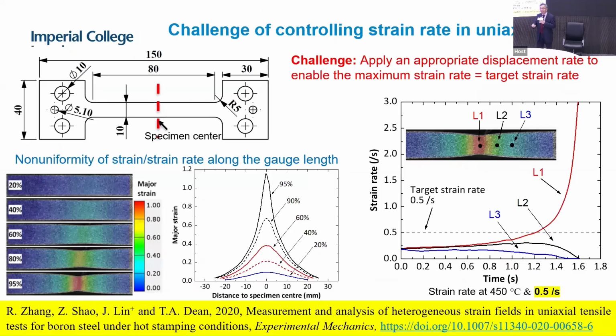And we use the DIC method to get the strain fields and so on. But you can see this is the specimen, from the center of the specimen. This is the major strain. And if you look across these areas, the strain is not uniform. The strain is not uniform because of the temperature gradients. But we published a lot of papers, a lot of research on how to control the temperatures, and I'm not going to discuss this today.